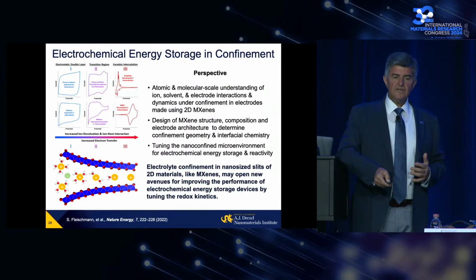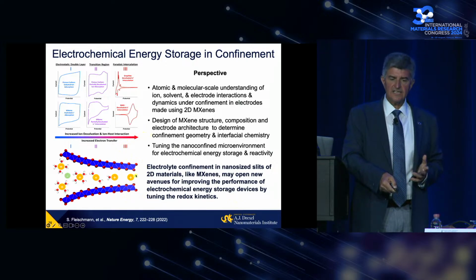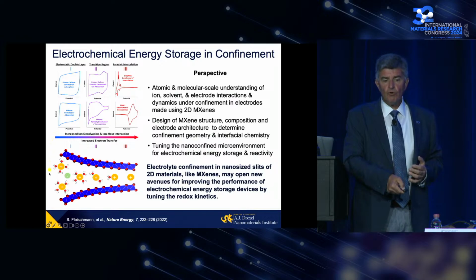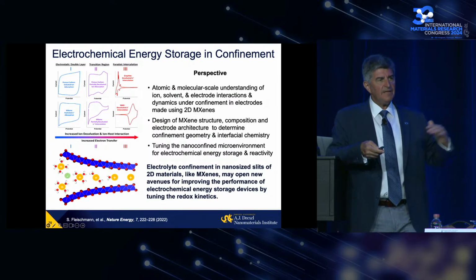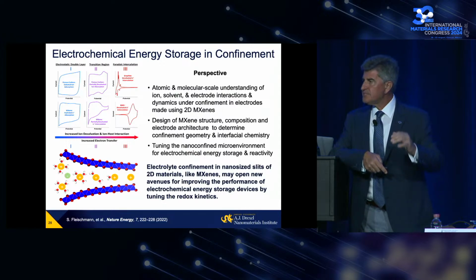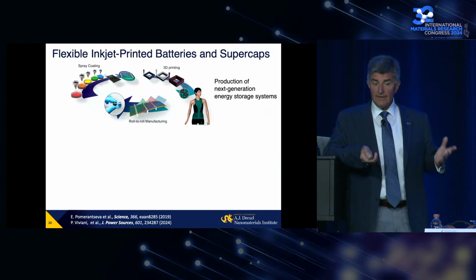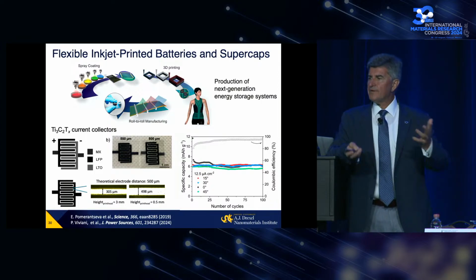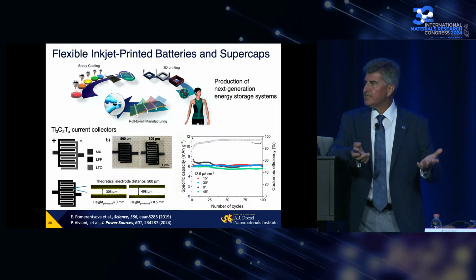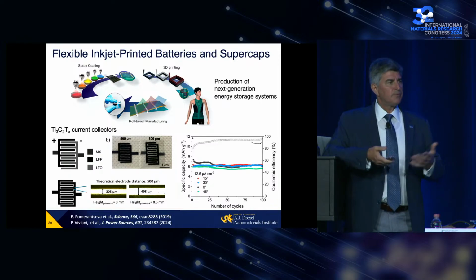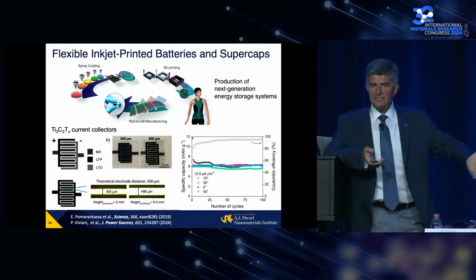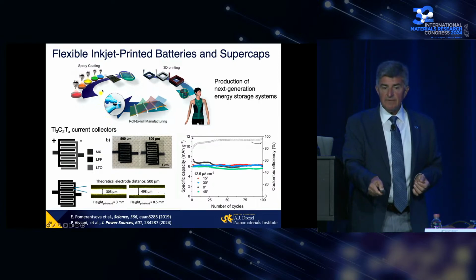Now we know how to inject ions, either intercalate like a lithium-ion battery between two-dimensional layers like in graphite, or get partial desolvation, get something we call pseudocapacitors, or get double layer capacitors, again by simply controlling the material surface chemistry and the electrolyte. And what is important, you remember I mentioned all the solutions that we can very easily print, ink-jet print, 3D print, process by any other ways. We can again paint it on the walls.